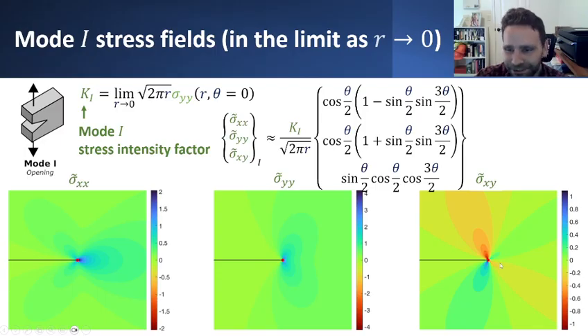And the shear stresses, there's certainly infinite shear stresses. Ultimately, though, it's still the yy stresses that are driving crack opening. These are the stresses that would actually result in crack extension, and these are the stresses that you would look at if you were interested in figuring out whether there is going to be some kind of increase or separation in the material. So the mode 1 stress intensity factor leads to these particular stresses in the material, in the limit as r goes to zero.